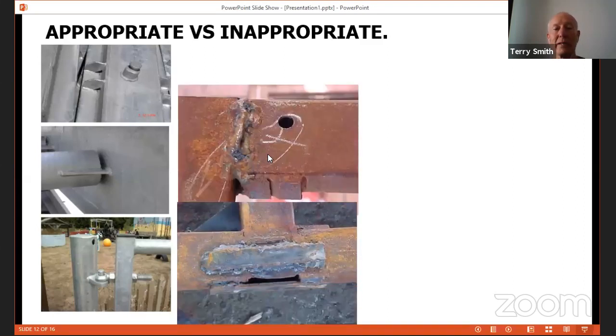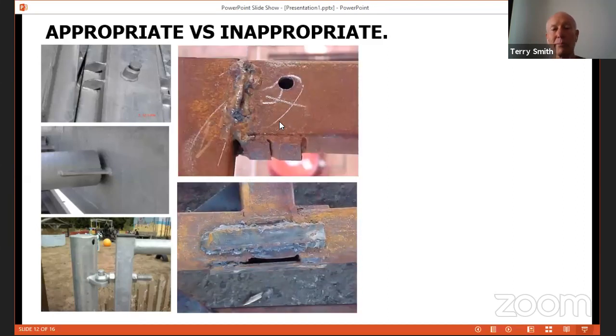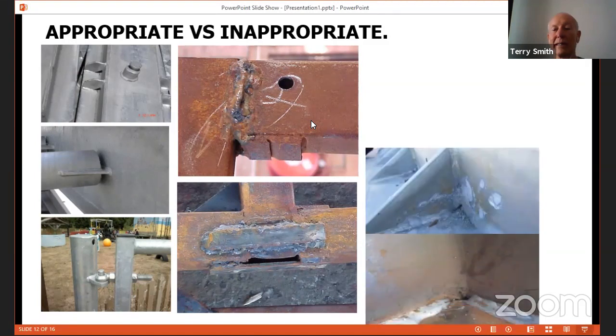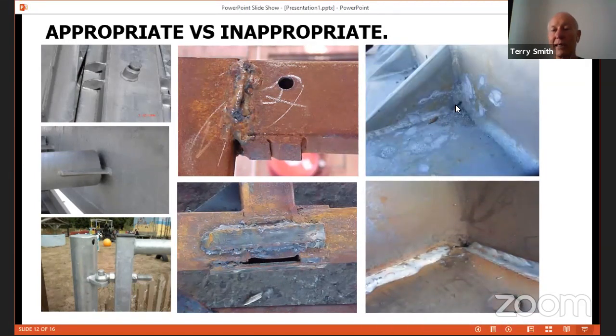And this is the less appropriate type of fabrication that we get coming into the galvanizing plant. What the guys don't realize is that all the weld slag here and here, little holes, etc., and that hole not being in the right position can lead to very bad galvanizing, much the same as this. You can see these coping holes, very small. You've got ash in the surface, and this one as well.